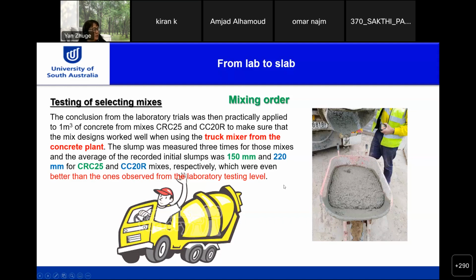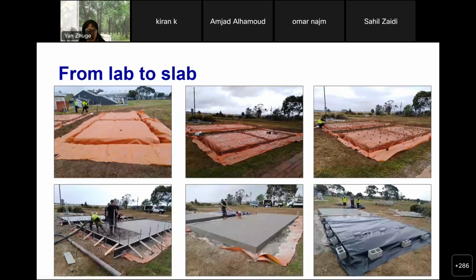The slump was measured 3 times for those mixes, and the average recorded initial slump was 150 mm and 220 mm for the CRC25 and CC20R mix. And also, they were even better than those observed from laboratory testing. That's why I tell you, when you have large quantities and use the truck mixer, the workability actually improved compared to the laboratory testing. And this is a real construction of a slab.